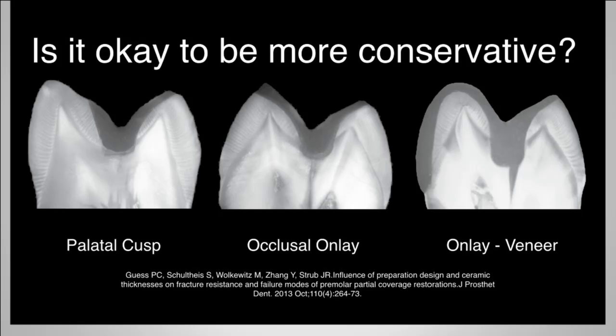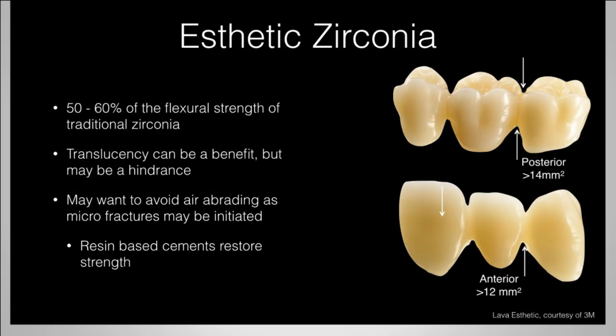Whenever we can preserve enamel, we must consider doing it. The more enamel we prepare and the more dentin we get into, the more dentin flexes. As dentin flexes, fractures can occur from the inside out, so from the dentinal interface out towards the ceramic. So general rule of thumb is, the deeper we get into dentin, the more thickness in ceramic we need. The more we're in enamel, the less thickness in ceramic we need. And we find that we do these thin restorations, and they work time and time again, and we preserve a lot of tooth structure.